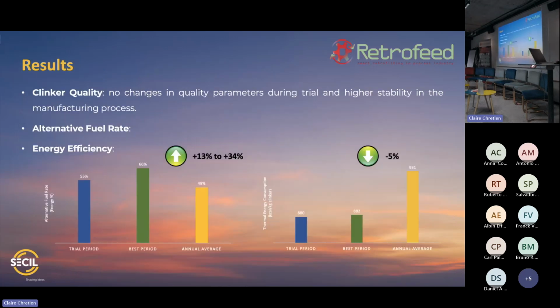And jumping directly to the results, you see here the annual average of 2023 of substitution rate, as I said before, around 50%, so 49%. And during the trials, we found that it is possible to increase the rate from 13 to 34%. So in the best period, we have a 34% increase, which is also very interesting, with a reduction in thermal consumption of about 5%.